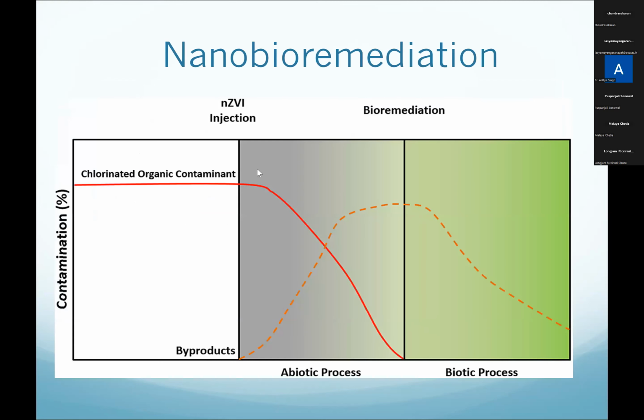The idea of nanobioremediation is that bioremediation does not work when the concentrations are very high. So let's say you have chlorinated organic contaminants, right? You have the concentrations, nothing is happening, it's not degrading. Microbes are there, but they don't want to touch this because these are high concentrations. And then why don't we inject the nano iron particles? You inject the nano iron particles, and then you see the contaminant concentrations decreasing, and you have byproducts